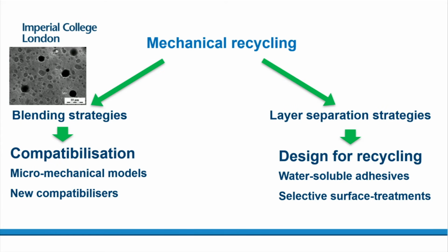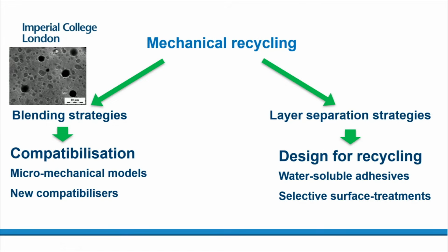And within that project, there's two things that we thought that we could do to try and solve this problem. Here I have a picture from literature which shows what you get when you try and blend PET film together with a polypropylene film. So the PET separates out into these particles in a continuous polypropylene. The reason why this material is not very strong is because there's not very good adhesion between the two phases.